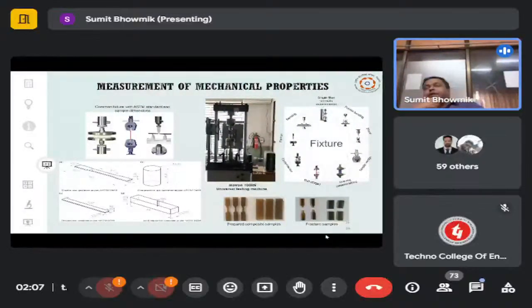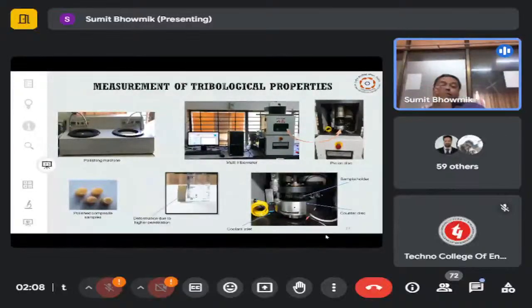Next, after the physical characterization, we come to the measurement of mechanical properties. In most cases for our material, we have conducted tensile and flexural tests. Flexural testing means the bending stress development under a pure shear or pure bending moment condition. This has been done in a servo hydraulic universal testing machine with a capacity of 100 kilonewton, and the different experimental setups and prepared samples are mentioned here. The tribological behavior has also been studied in a multi-tribometer, which is pin on disc, and it is also carried out at different ASTM standards.